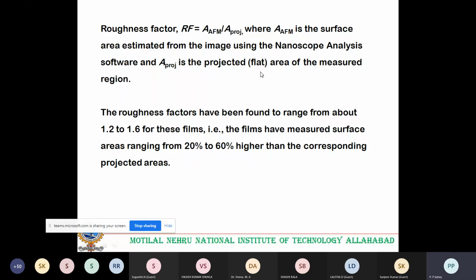And when you calculated for all the 3 films, we found that the roughness factor has been found to range from about 1.2 to 1.6 for these films. That is, the films have measured surface area ranging from 20 to 60% higher than the corresponding projected area. Okay, because the projected area we have taken 1 micron into 1 micron. But when you find out the image surface area, it was more. And that more means it is 20% to 60% higher than the projected area. And if the roughness factor is more, what we observe in our study is that it favors the enhancement in the electrochemical performance.